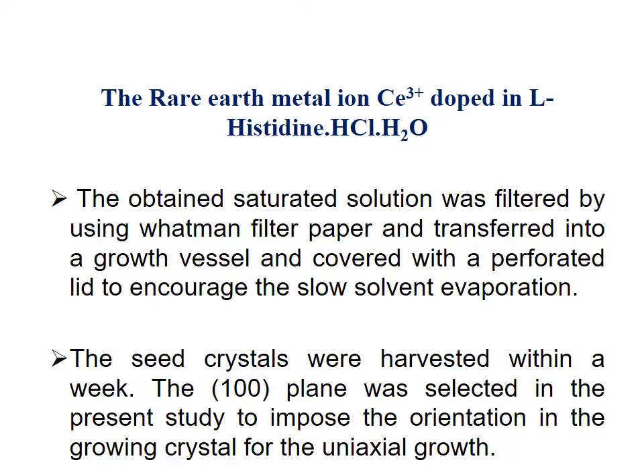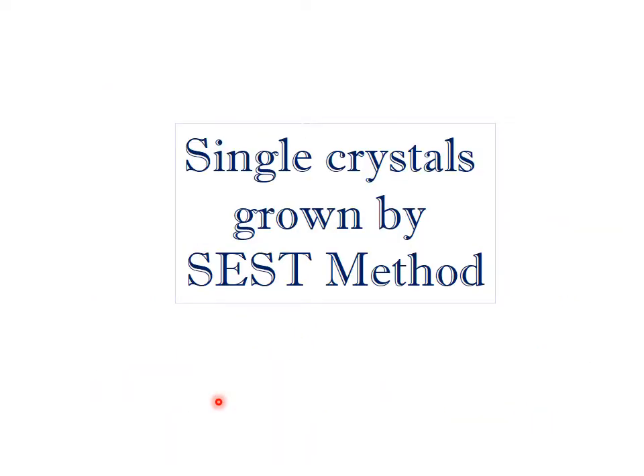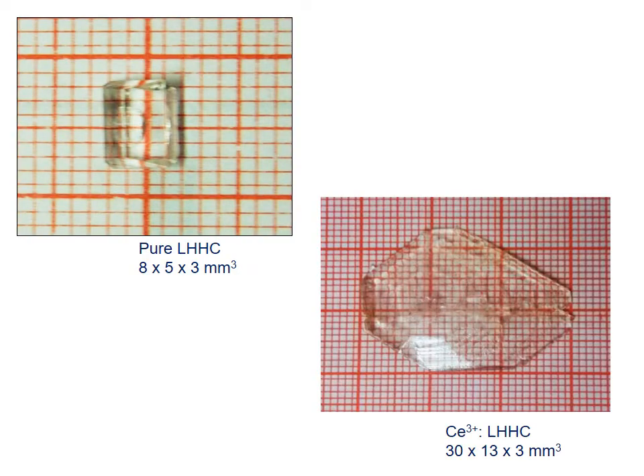Cerium is the rare-earth metal ion doped into L-histidine hydrochloride monohydrate. The obtained saturation solution was filtered using Whatman filter paper and transferred into a growth vessel, covered with a perforated lid to enable slow solvent evaporation. The 1-0-0 plane was selected for uniaxial growth orientation. Crystals grown by slow evaporation solution technique: pure L-HHC with dimensions 8×5×3 mm³, and CE3+ ion-doped L-HHC single crystal with dimensions 30×13×3 mm³.